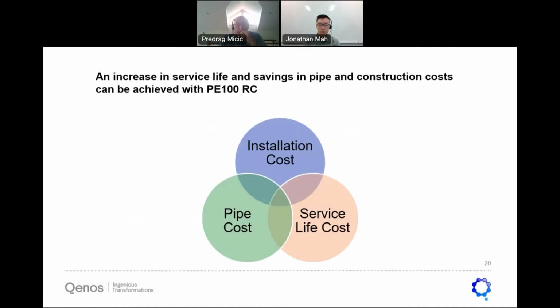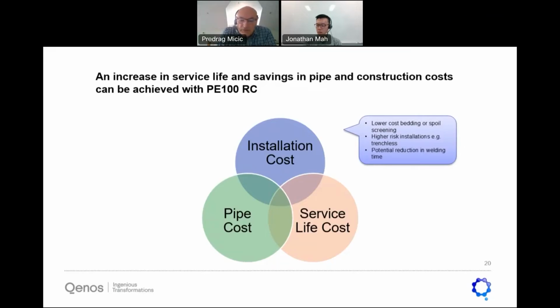But there are many ways how PE100 RC and this increased toughness, because as I said, this is what the whole industry worked on, because it is a relevant property, can contribute to our designs and cost effectiveness, and increase in service life and savings in pipe and construction cost can be achieved with PE100 RC in all areas. So we can have a lower installation cost because of the bedding or spoil screening. We have high risk installation, trenchless, and potential for the reduction of welding time, if we are not over designing our pipes. And very often I can see pipes of PN25 in horizontal directional drilling application. The pipes that will operate at 8 bar, we're using PN25, SDR9 or even thicker pipes, so we're building that through the wall thickness, which is probably not the best integrity measure.